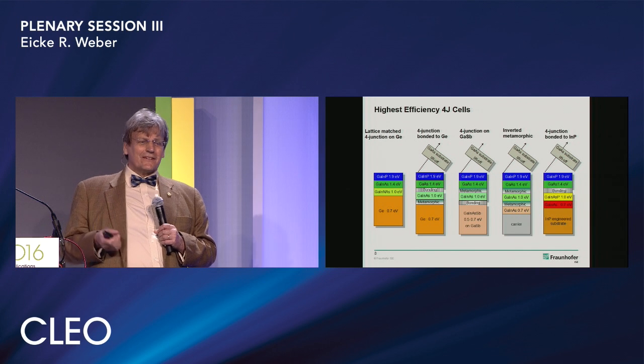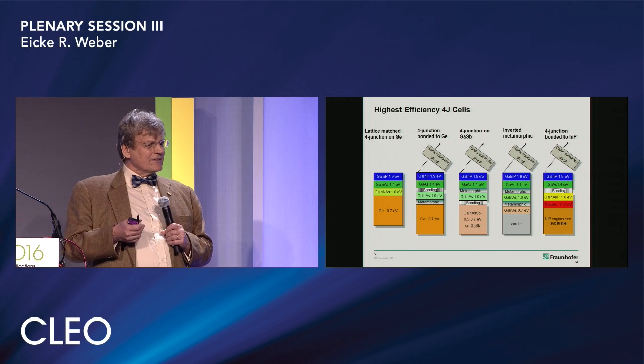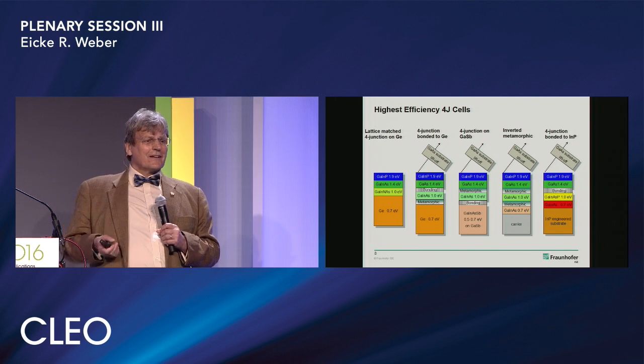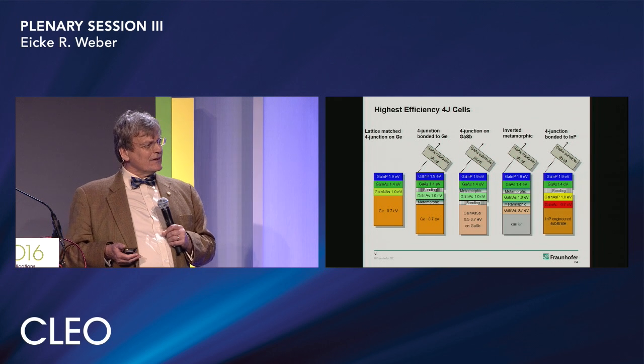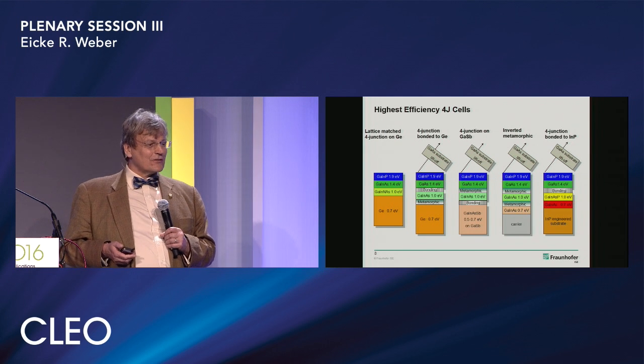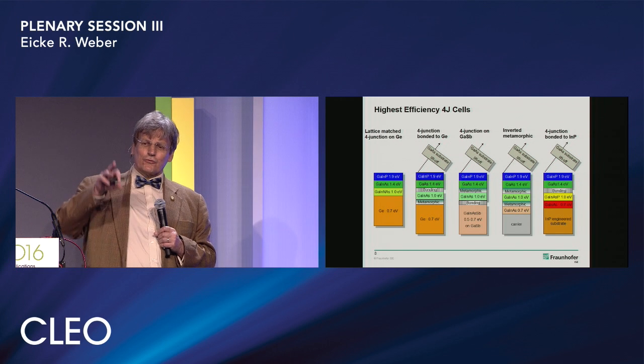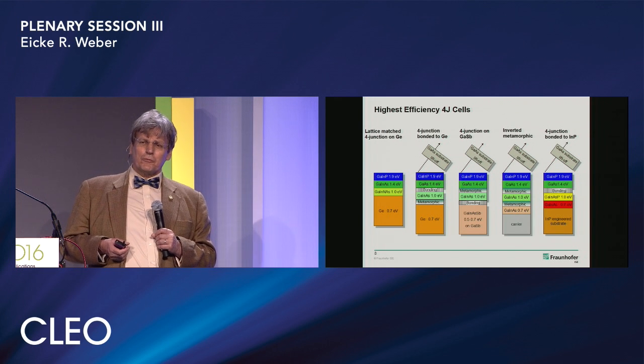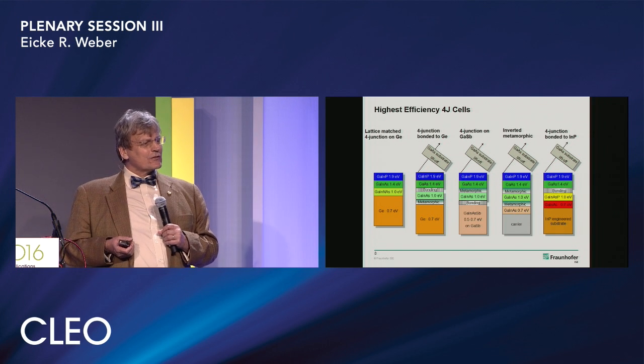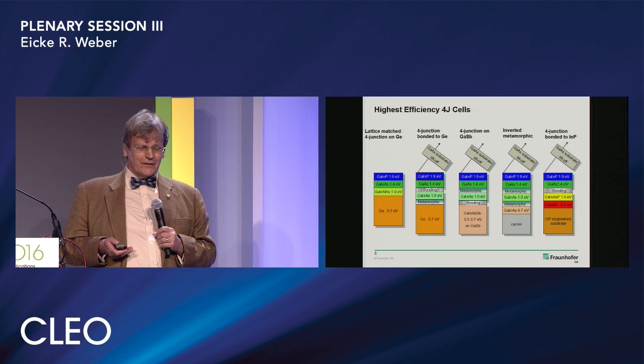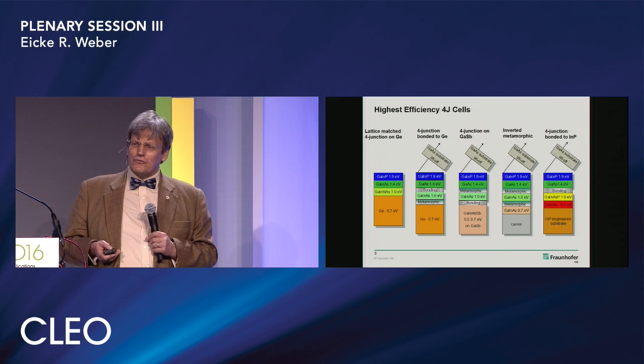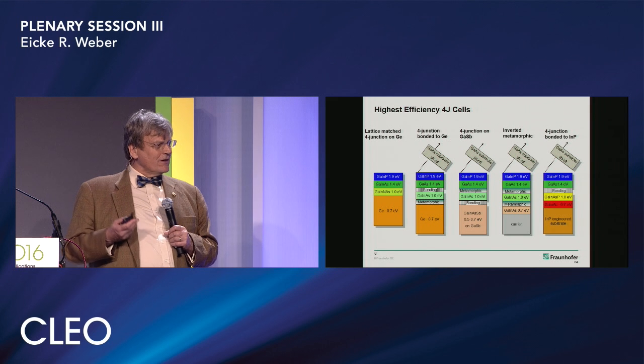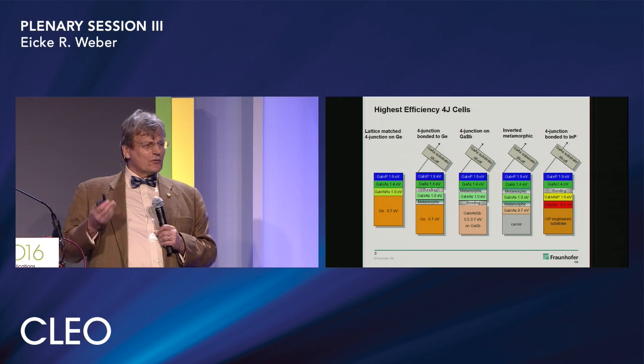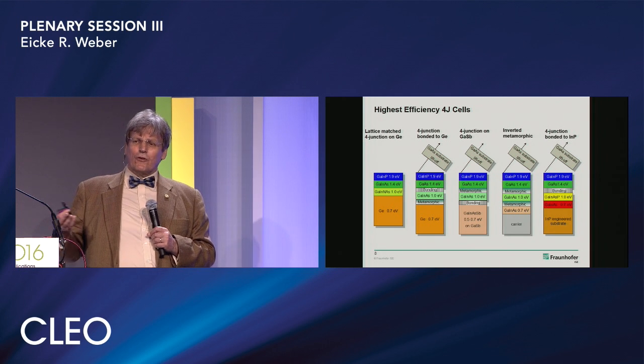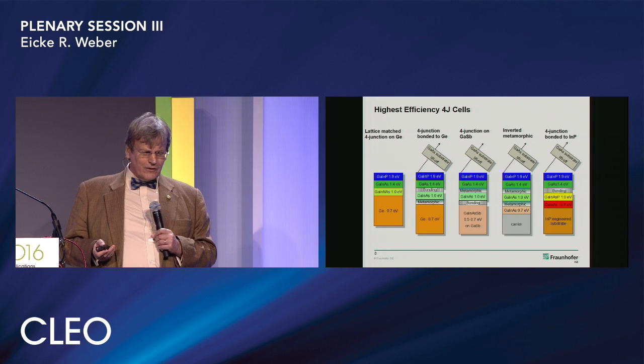And of course, this might work well for silicon technology, where at the end, the carriers stay in the active layer near a field effect transistor. But in a solar cell, where the carriers have to go through the whole structure from top to bottom, they have to go through this artificially created bonded interface. But as I will show you very soon, this wafer bonding technology is today at the level we need in order to be able to make high-quality solar cells.